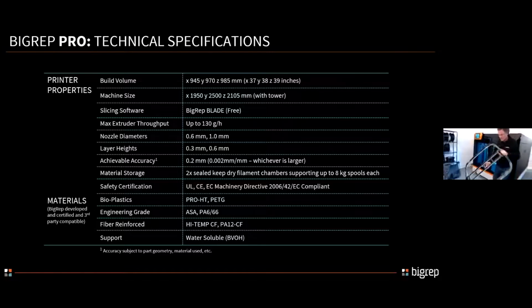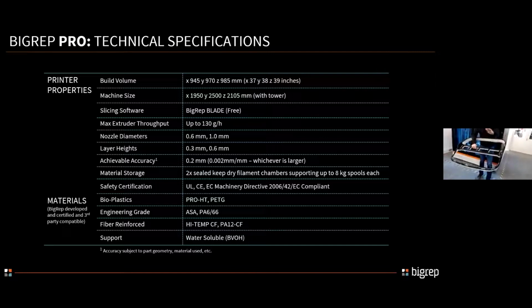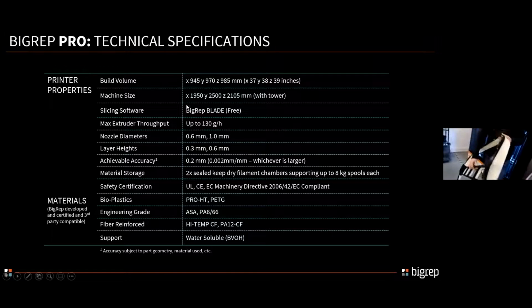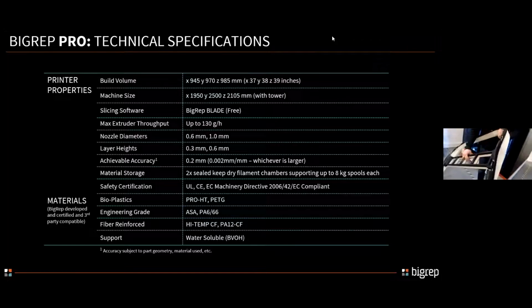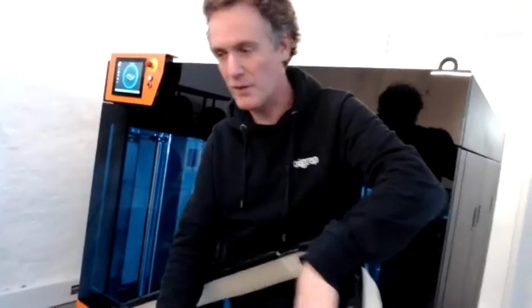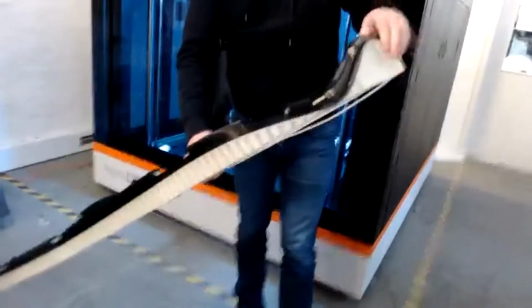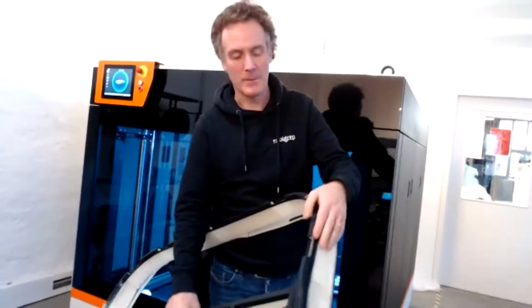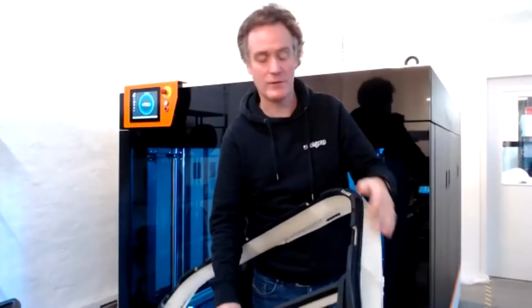So what you see here is a fixture that one of our automotive clients is using, and this is printed in PA6/66. PA6/66 has very nice mechanical properties. It is very strong also in the Z direction. Sometimes what happens with 3D printing is that you have delamination. With nylon, you really don't have that at all. It's a very shiny material, therefore you see all of the printing. We actually like that a lot here. It's very different from what Marco was showing before on the PA12 part. You don't really see that. It's much more matte, and it's a very different finish.